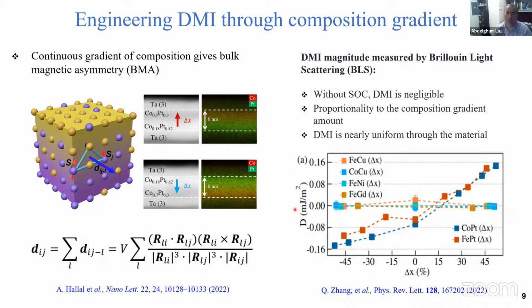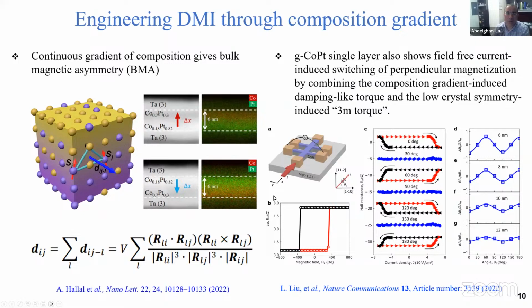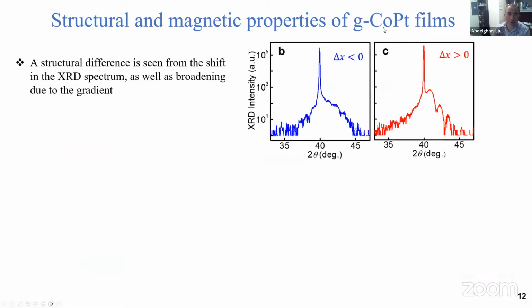That's a very good question. In principle, from XRD you can see the cobalt platinum peaks. The fact that you have some narrow peak means there is some order. You just see broadening at the sides due to this gradient change. But I think I have it here.